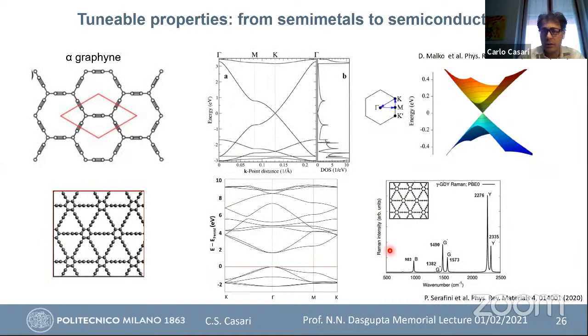And again, theoreticians were very interested by this. For example, in 2012, the group of Malko reported this, showing the presence of Dirac cones in this alpha graphyne. And in the same way, this is, for example, the gamma graphdiyne, one possible structure. This, for example, is semiconducting, and also you can predict the Raman spectra.